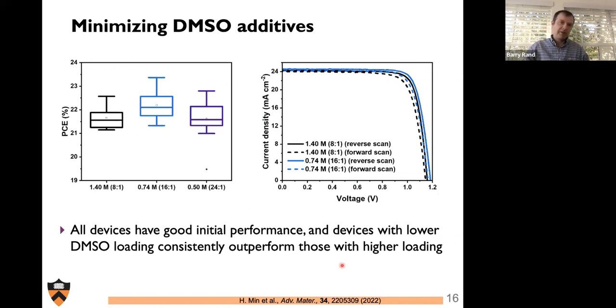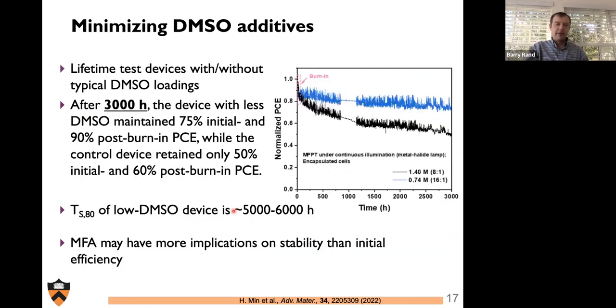Regarding their initial performance, we find that, statistically, it's really hard to find very meaningful differences between a small amount of MFA being incorporated in these films and not much at all. So the device with lower molarity leads to slightly better performance on average, but I would say that they all perform pretty admirably in this device structure. However, where they really start to diverge is with regard to their stability.